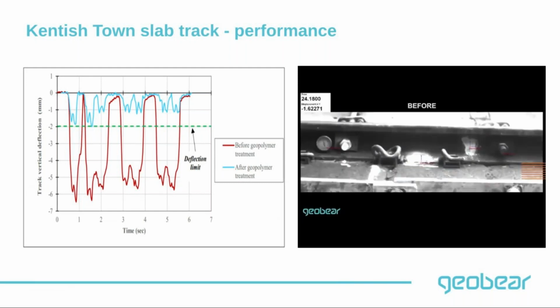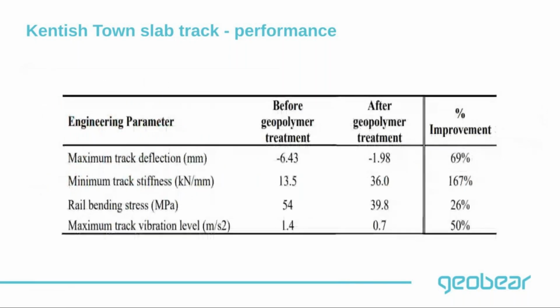If you carry out some simple back calculations, you can see that we've managed to reduce track deflection by up to 70%, improve track stiffness by 167%, reduce rail bending by 26%, and reduce track vibrations by almost 50%. So it's quite a significant improvement.